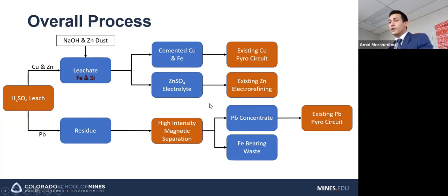The residue, which contains the lead, we are going to subject to WHIMS, or it's a magnetic separation. I forget what it stands for. And the reason we're doing that is to knock out some of the iron that's in that residue. And so we get two products from the magnetic separation. We get a lead concentrate and an iron-bearing waste. The lead concentrate is still mostly a lead sulfate. And so there's a few things we can do with that, but both involve putting them back into the existing lead pyro circuit. We could feed them in as a bleed stream to their center plant.